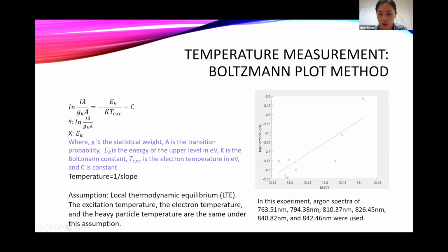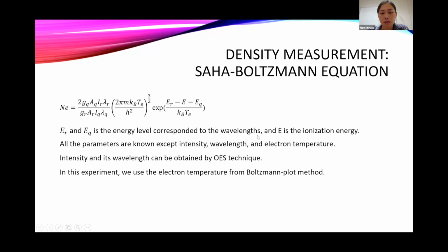We make the scatter plot and use a linear fit, because the temperature of the electron is going to be 1 over the slope of the linear fit. And the important assumption for the Boltzmann plot method is local thermodynamic equilibrium. Under this condition, the excitation temperature, electron temperature, and heavy particle temperature are the same. And for density measurement, we use the Saha-Boltzmann equation. This is very simple. And we know all the parameters in this equation.